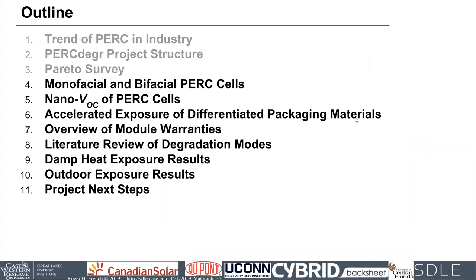All right, and then I also asked people to list additional areas of concern, so I think I've mentioned a few of those. In terms of PERC module reliability and durability, some of the things that people brought up were, they'd like to see better characterization in terms of actual energy yield in the field instead of just focusing on standard test conditions. So looking at things like low light level performance related to shunting effects, spectral effects, operating at a higher temperature. So that was one. Another was related to one of the options, development of meaningful accelerated test methods to predict failure mechanisms. So kind of improving those accelerated testing techniques. Also the reliability of transparent backsheet materials for bifacial modules. So if we're shifting from glass-glass to glass-transparent polymer, what's the reliability of that?